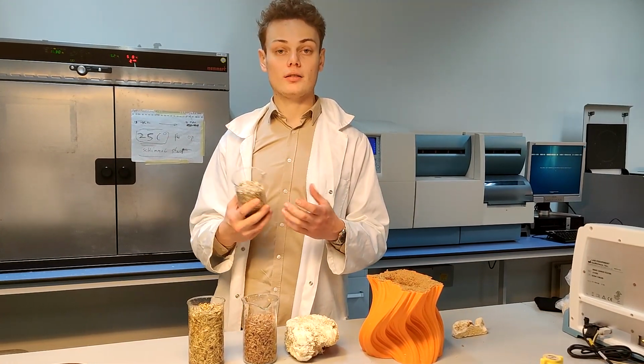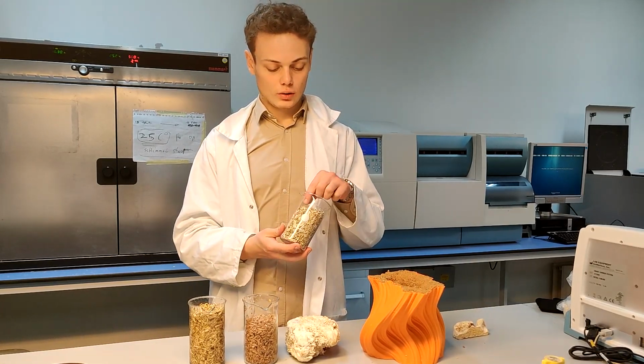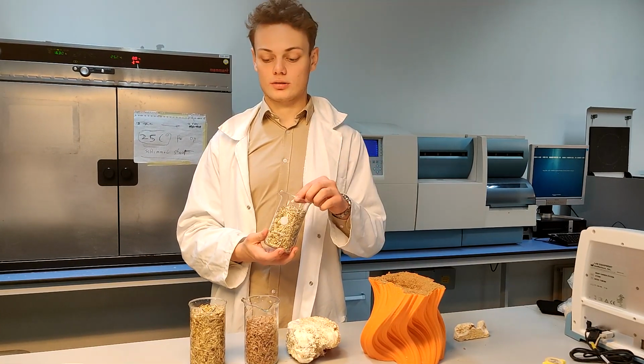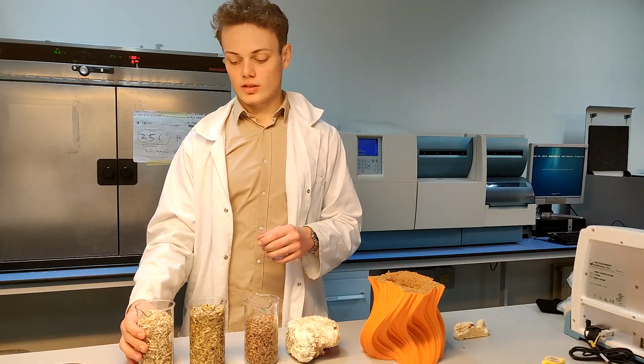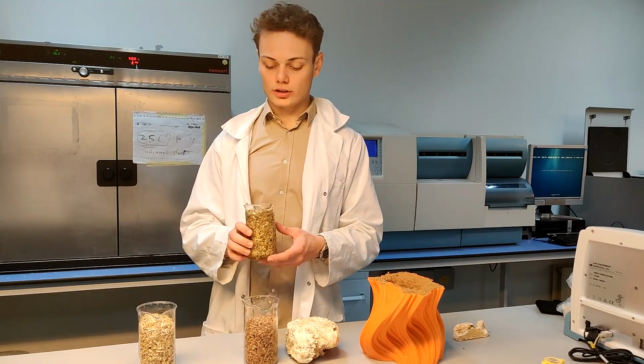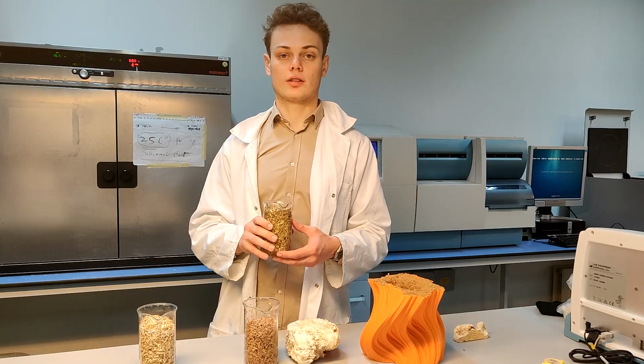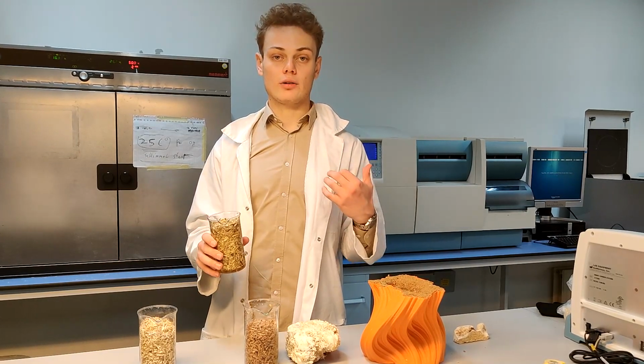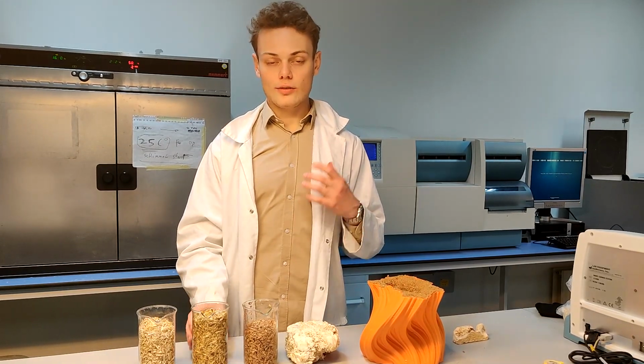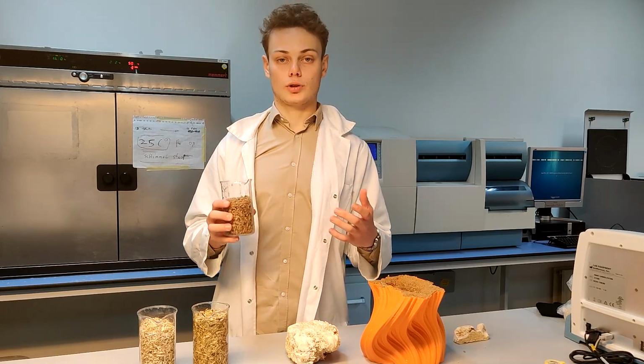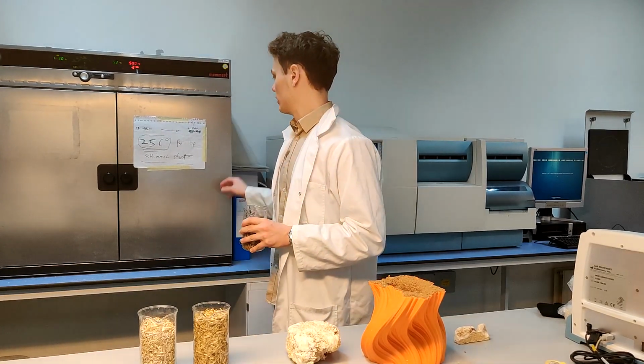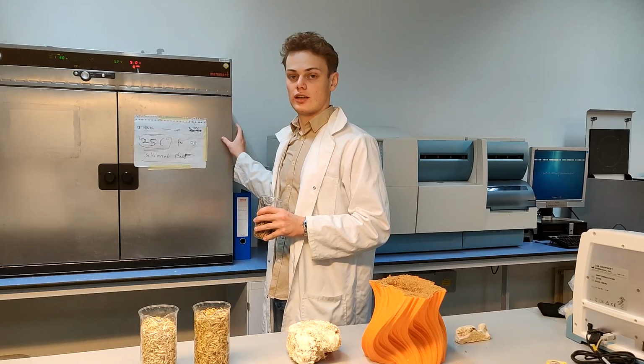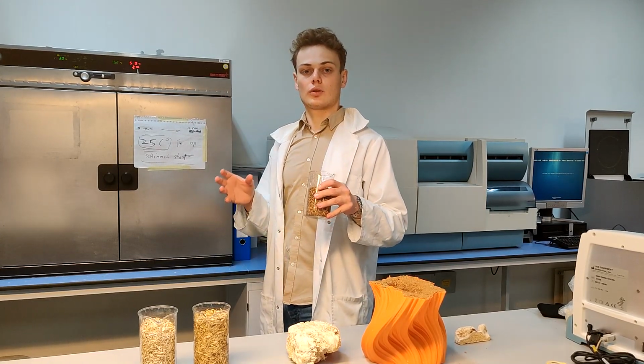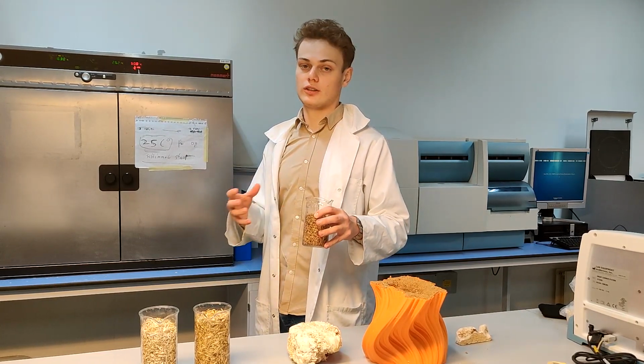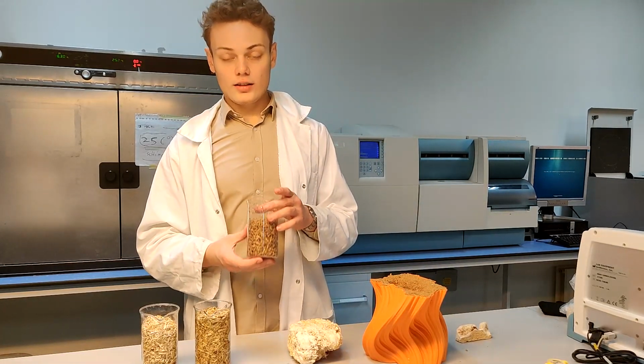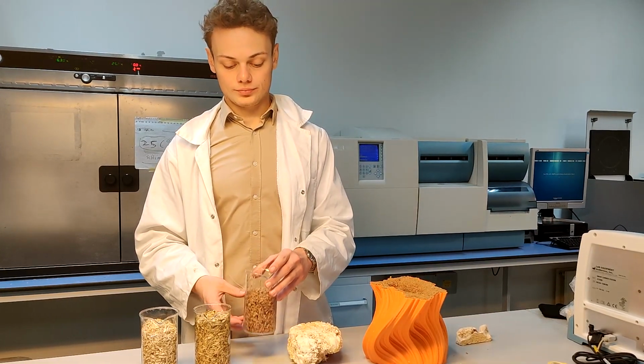These come pre-shredded to about a size of 10 millimeters. At first, the material is cooked to fully sterilize it. This prevents contamination later on in the process. After this, it enters a phase we call pre-growth. In pre-growth, we put the hemp fibers in a chamber that has a controlled temperature and humidity. In this chamber, the mycelium starts growing.